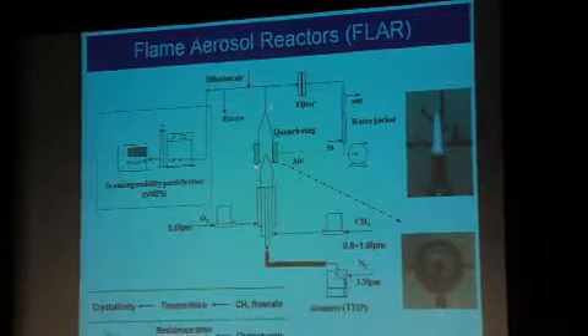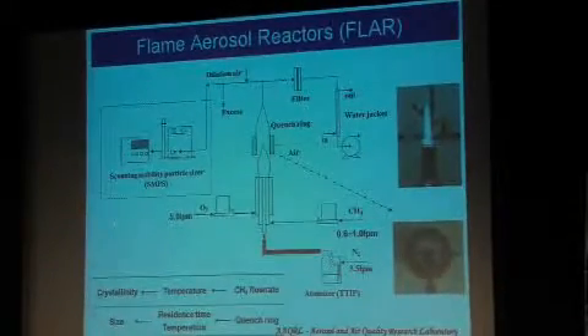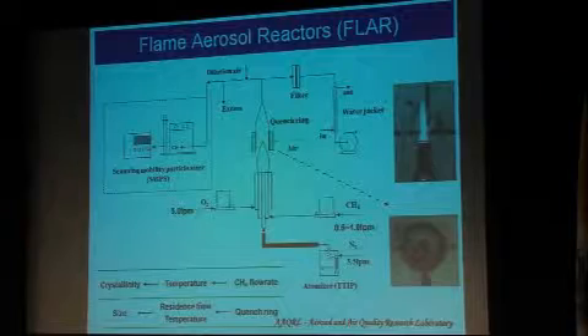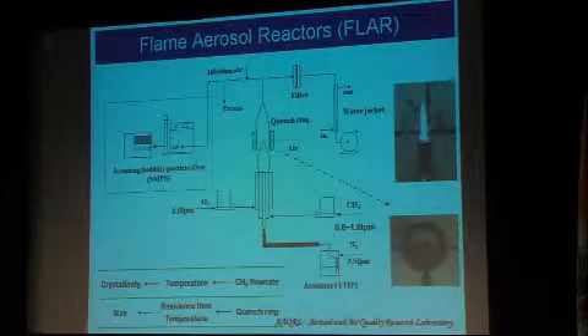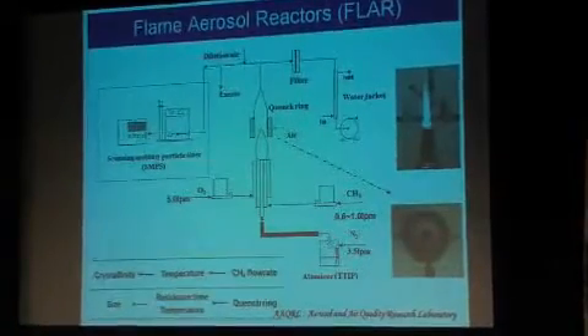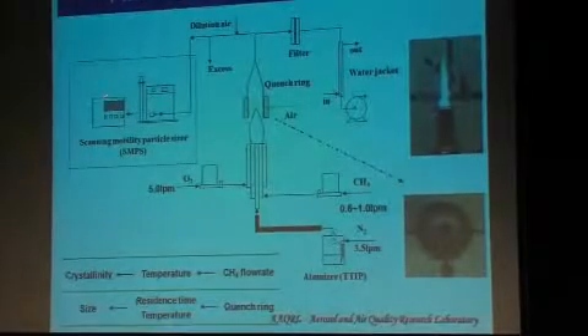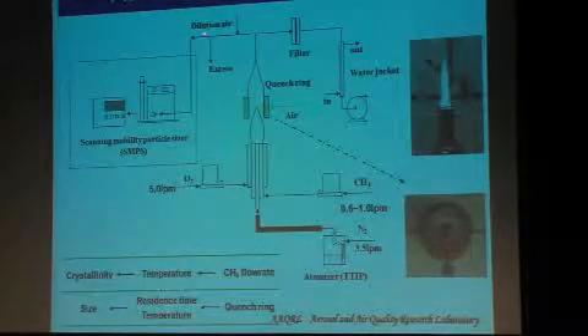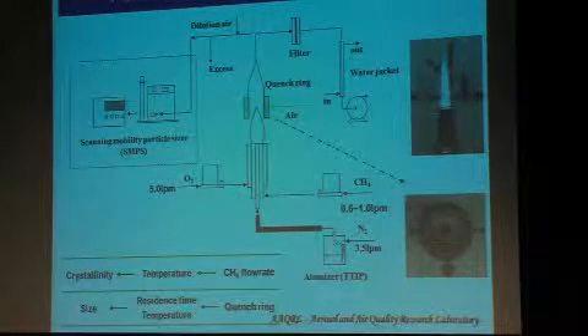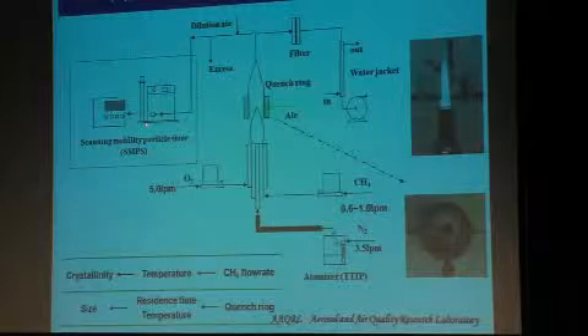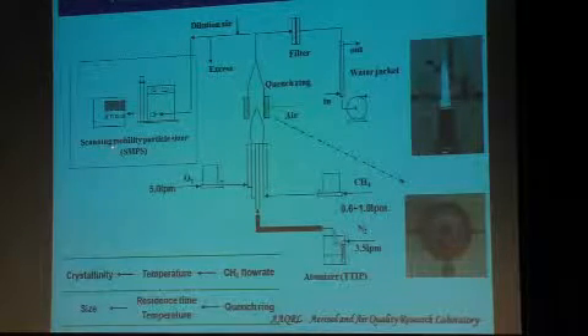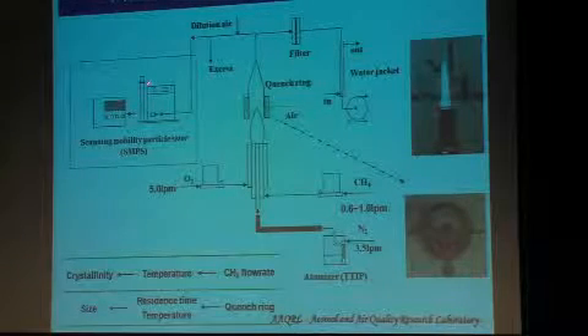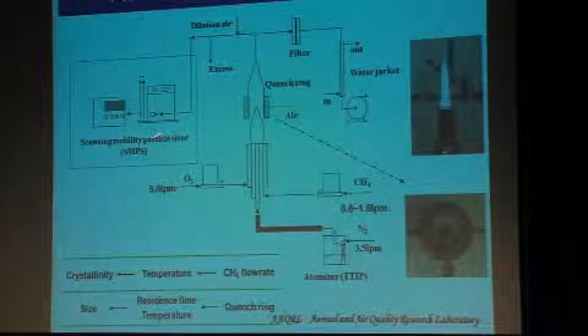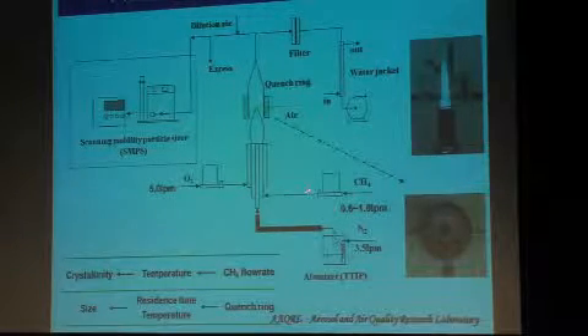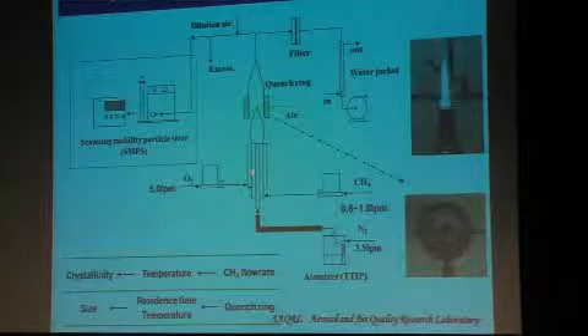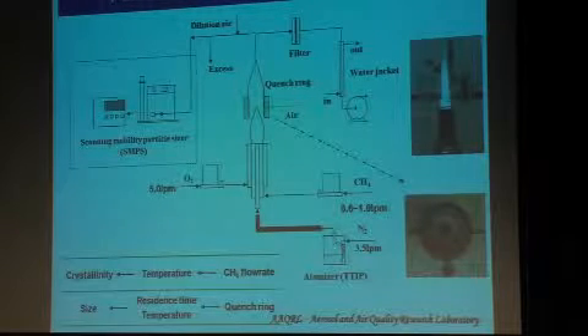Flame reactor, very similar. This is a quench ring which allows us to control the temperature gradient. And I want to point out these real-time aerosol instruments. In some sense, at least in the gas phase, our measurement techniques have evolved. Maybe it's a simpler measurement in some sense compared to in aqueous media, but some of these instruments are now very widely available. In flight, I can pull out some particles, place a charge on them very precisely, and classify them by size in an electrical field, and then count them very precisely. This can count down to a single particle. I can change the voltage and get different sizes, count them, and get the entire size distribution. This could be done in less than 1.5 minutes. Some of the newer instruments have fast scans. I can do it very rapidly, so I could do a dynamic measurement and see how my reactors are changing